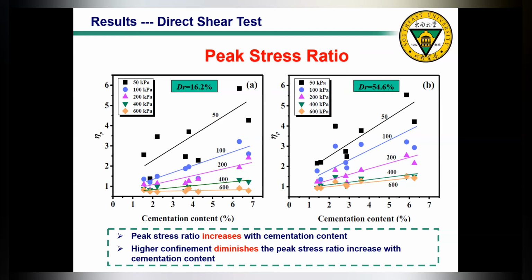However, this increase is diminished with higher confinement. For 50 kPa, we can see the slope is quite large, so this increase is quite significant. However, at 600 kPa normal stress, with increasing cementation content, the improvement in peak stress ratio is not that significant. So this diminishing effect is obvious. And finally, it seems the initial density does not have an obvious impact on the peak stress ratio.